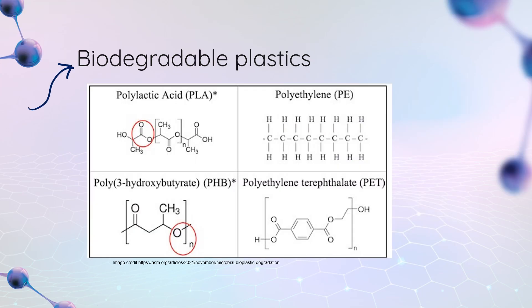We're trying to design more biodegradable plastics. One way to make a polymer like polyethene more biodegradable is by adding functional groups that attract bacteria, like an ester group. The ester in PLA — polylactic acid plastic — helps attract bacteria and allows decomposition to happen much more quickly than in regular polyethene. One challenge is that in a landfill with low oxygen concentration, bacteria can't survive, so decomposition won't occur as desired. Another challenge is that biodegradable plastics can produce methane as they decompose — a greenhouse gas — so we're switching from one environmental challenge to another.